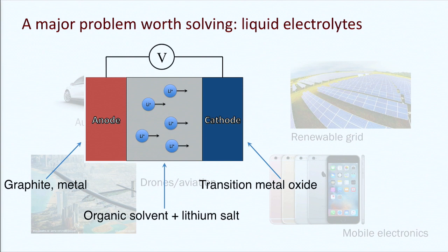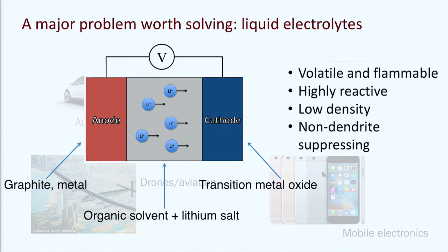These organic solvents are great for a number of reasons: they're very cheap, already manufactured at scale, and have great lithium transport properties. But they are also not great for a number of reasons, including that they are volatile and flammable — that's where you get a lot of your safety issues. They're highly reactive, liquids in general are sort of low density, and they don't suppress dendrites, which is one of the main causes of early death in lithium-ion batteries.